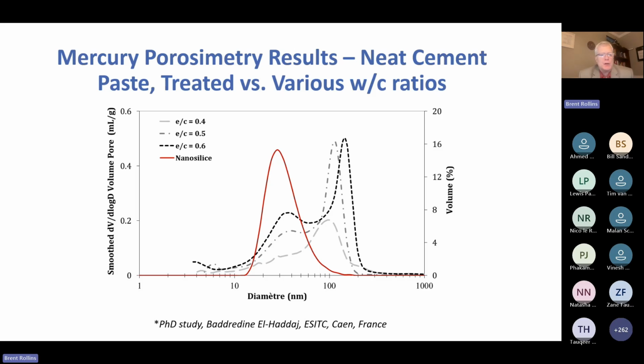The colloidal silica, what they're calling nanosilice in French, was applied to the surface of the neat cement paste, and then the pore structure was examined again a few hours later, and you can see that the average pore diameter went from being above 100, and it was the 0.6 that was treated, by the way, with the colloidal silica. The 0.6 was adjusted from well above 100 nanometer pore diameter down to about 30 nanometer pore diameter. So that reduction in pores in a neat cement paste is a demonstration of what the product can do for concrete. So this was ESITC in France, and they're one of the top technological universities in that country.